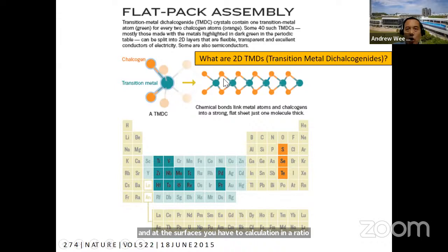And the chalcogens can arrange themselves in a hexagonal or tetragonal way, and these are different phases. So, for example, in many TMDs, the 2H hexagonal phase is semiconducting, whereas the 1T tetragonal phase is metallic. And because you can have many of these 2D TMDs, you get many different properties. And in fact, there are also many other 2D materials.